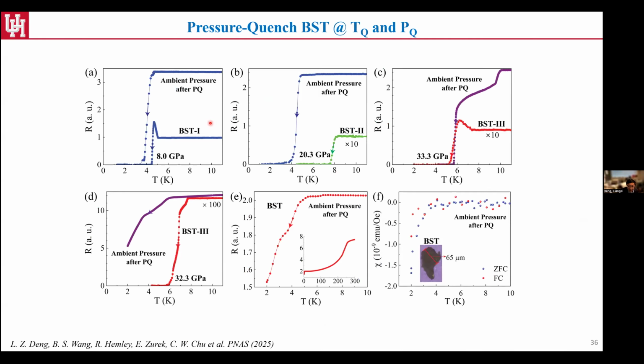So surprisingly, even though I put the order from 1, 2, 3, when we're doing quench, as I mentioned, we do the quench from the second phase and the third phase first, and we're able to retain the superconductivity. That lines up with the hypothesis that the structural transition really helps to create the energy barrier that locks in the high pressure, high TC phase. But the more exciting thing is actually for the first phase, there's no structural transition. There is a possible electronic transition, but still we're able to retain this high pressure phase at the ambient condition. That's really surprising, but also interesting to us, right?